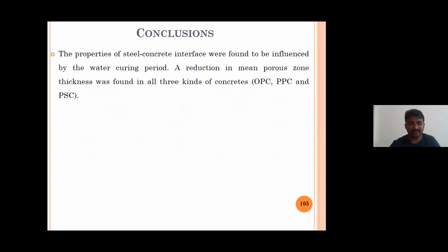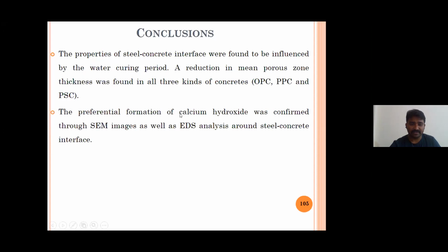The properties of the steel concrete interface were found to be influenced by the water curing period also. As the curing period increases, the Ca by Si ratio is decreasing. That means some amount of hydration reaction is still happening at the steel concrete interface even after a curing period of up to 1 year. The reduction in mean porous zone thickness was found for all three kinds of concrete. The preferential formation of calcium hydroxide was confirmed through SEM images as well as EDS analysis.